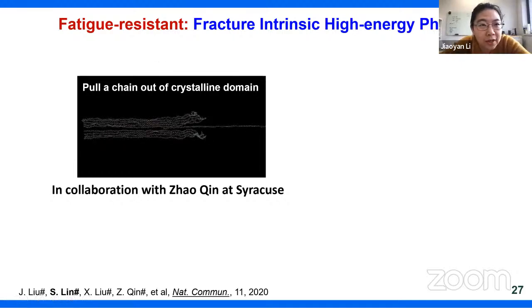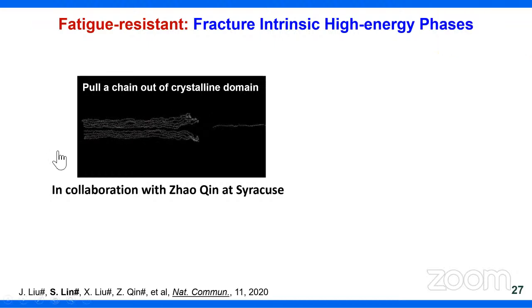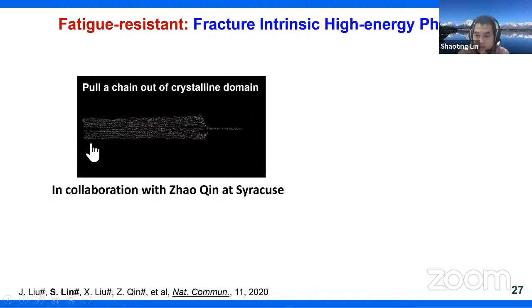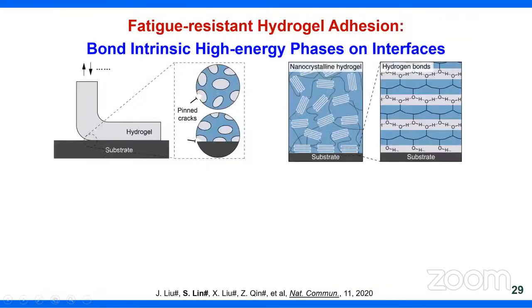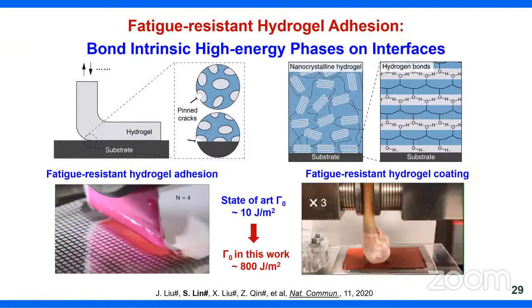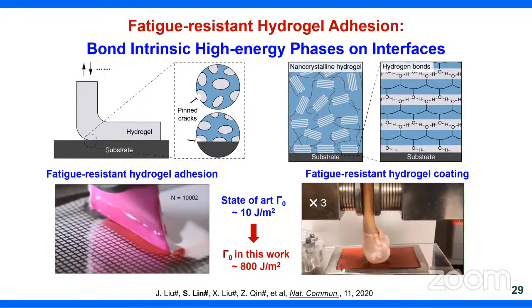Okay, so please feel free to unmute yourself and ask your question. Hi, thank you for your fantastic talk. I have a question about page 29, about the hydrogel adhesion. I understand that if you introduce the crystalline domains into the hydrogel, you increase the fracture toughness, but how can it help the adhesion, since you didn't change the substrate? You measure the adhesion between the substrate and the hydrogel. There's no crystalline in the substrate, right? You just introduce some crystalline into the hydrogel, so you can still increase the adhesion. What's the reason?